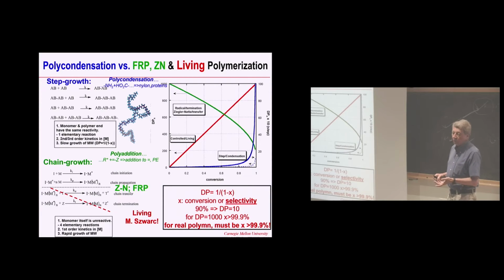Or you can add another monomer and make a block copolymer. So at that time, it was really like a revolution in polymer science because nearly nobody before could make block copolymers because they hate each other. They macroscopically phase separate, but in a case of a block copolymers, they would phase separate on a nanoscale, on a scale of nanometers, essentially. So this was beginning of nanotechnology in some sense. Again, this equation, Carothers' equation, has a little bit different meaning. X is not conversion. X is a fraction of the chains which can continue to grow versus some other chains. So in order to get degree of polymerization 100, you need to have a 99% selectivity of propagation over chain breaking reactions.